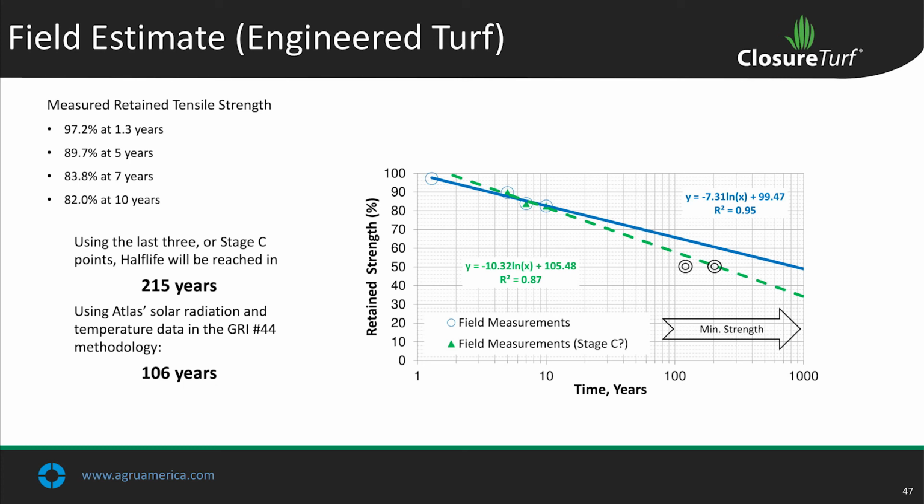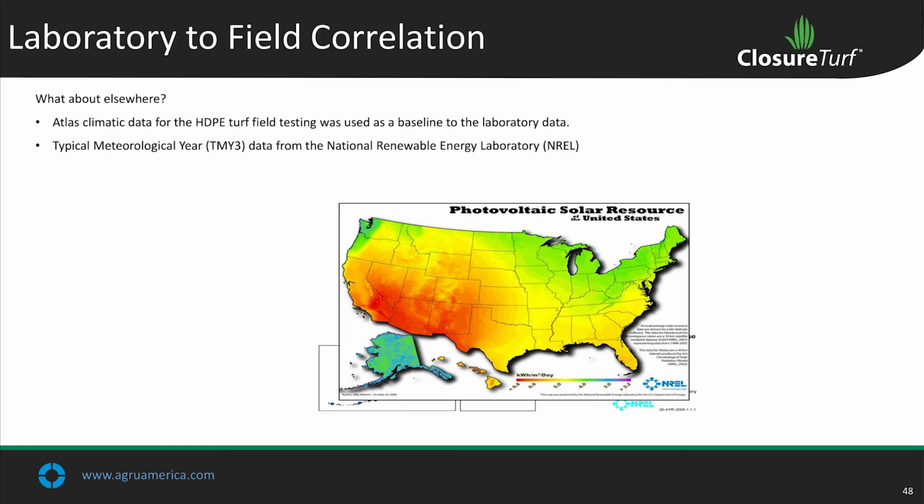So this is pretty much agreement. When you consider the minimum strength required in the turf component to hold the whole system together, the sand ballast and the geotextile and turf and all that, we're talking a longevity that's on the order of centuries. I mean, till end of life is basically centuries. So, long time.